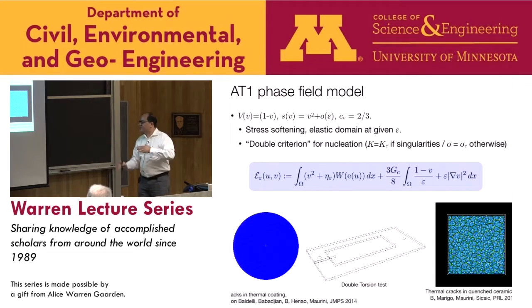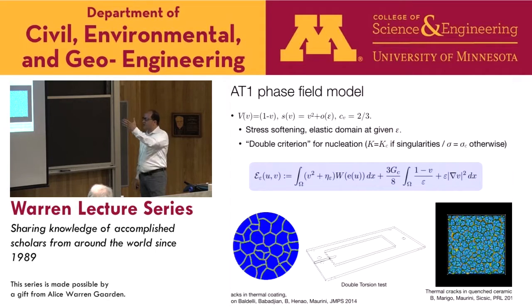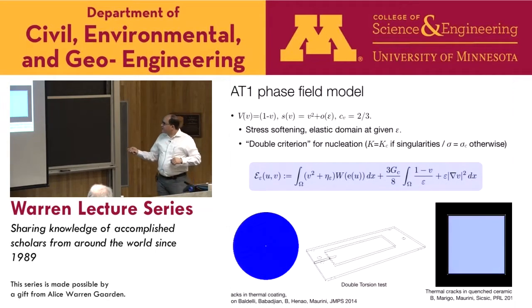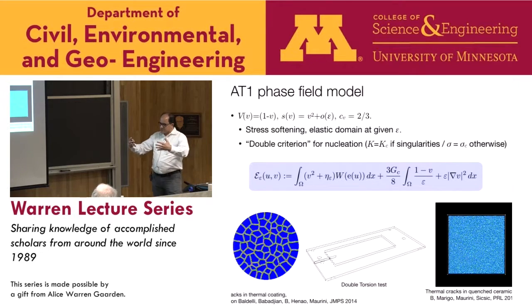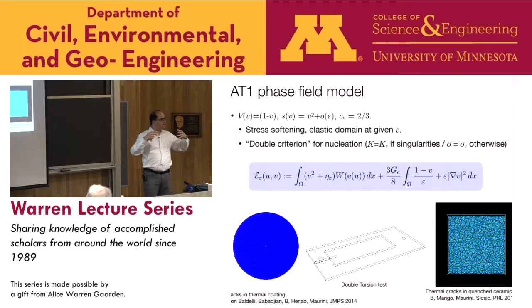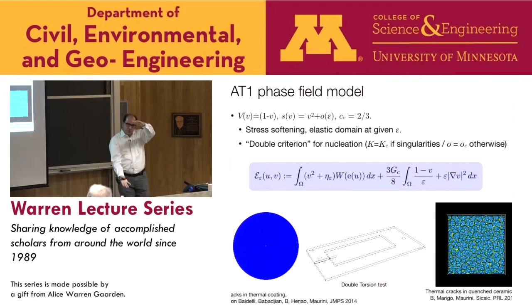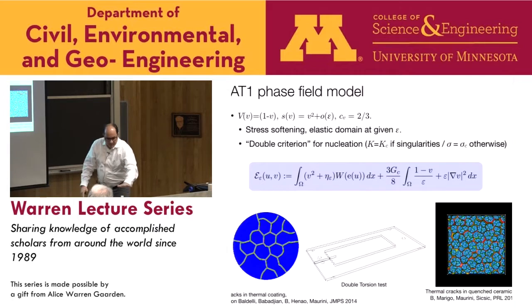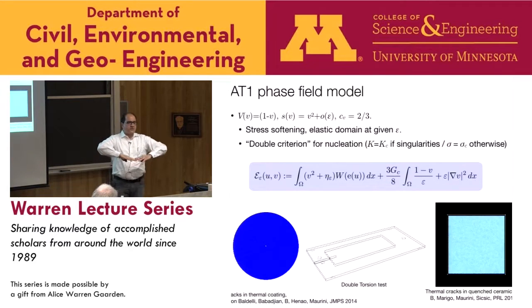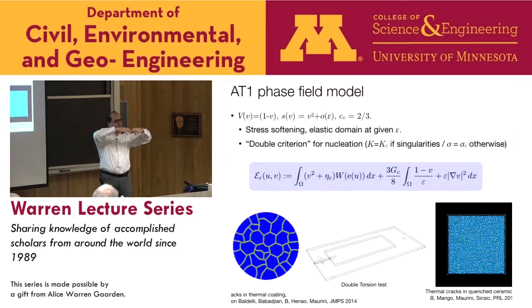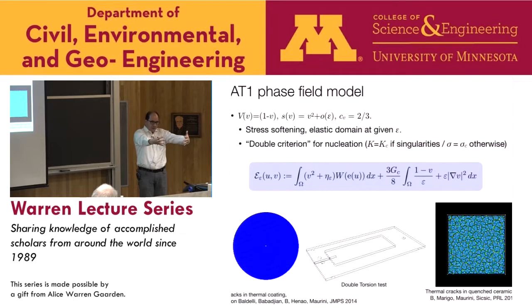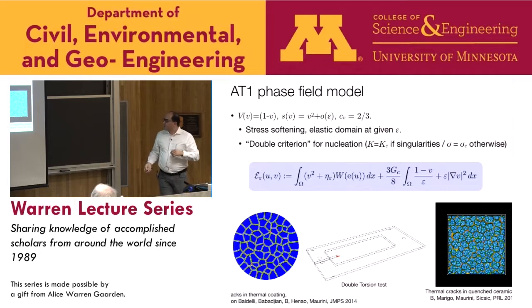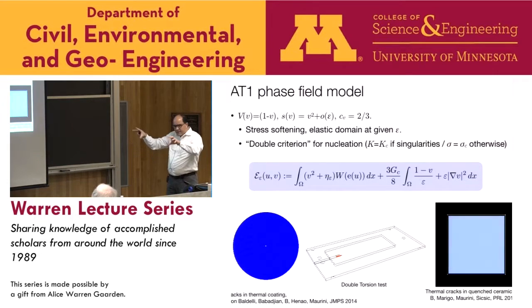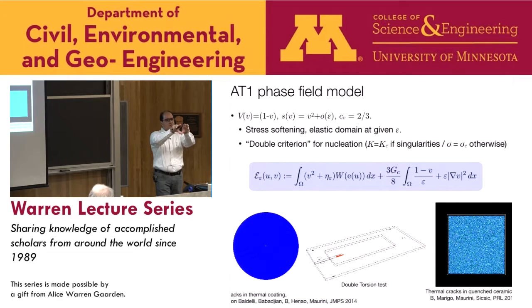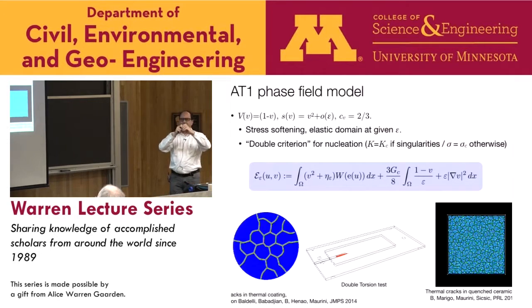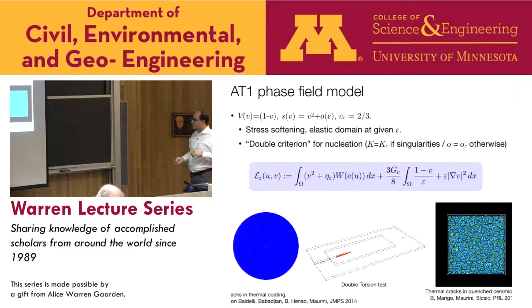This is an example where you see a 3D crack front that moves along an unknown geometry. This one is very hard to read at such a small scale, but it's the propagation of thermal cracks in a ceramic. Think of a block of heated ceramic that you quench, or put on a cold surface, so you have this cold front that propagates. It creates tensile stresses and it creates cracks. Here you're sitting inside your material and watching the crack front coming towards you. But you see the potential of this approach to capture this very complicated crack pattern, the nucleation of all these cracks, and the coarsening phenomenon that leads to larger and larger cells coming towards you.